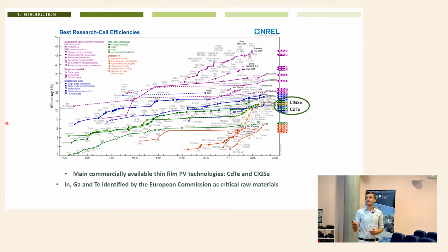Nevertheless, these 2 technologies have a big issue. They contain indium and gallium in the case of copper indium gallium diselenide, and tellurium in the case of cadmium telluride. And of course, cadmium is a toxic element. But indium, gallium, and tellurium are identified by the European Commission as critical raw materials.